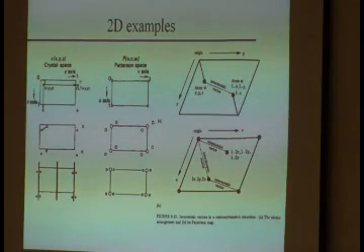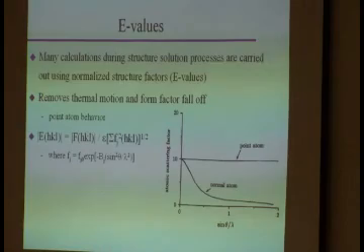Here are two atoms that are given with positions. And then your interatomic vectors can be given with respect to the distance between these equivalent positions. Now, do you usually use your measured intensities directly to plot a Patterson? As a matter of fact, in many cases people use something else. They use something called E-values. And the E-values are intimately related to the F values. The main difference is they are normalized.